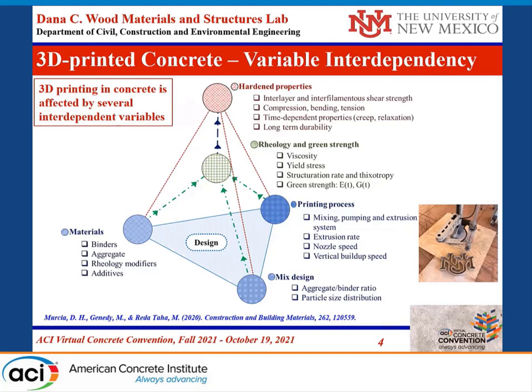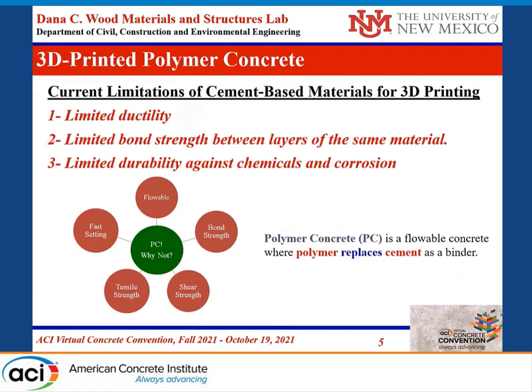Most work so far has been on cement concrete. We are looking at polymer concrete for a number of reasons: the limited ductility and cracking issues in normal concrete, limited tensile strength — polymer concrete allows higher ductility. Also, the issue of bond strength between layers in cementitious concrete can be overcome by the high bond strength typically available from polymers. Additionally, the limited durability against chemicals and corrosion in normal concrete can be overcome because polymer concrete is impermeable at large.